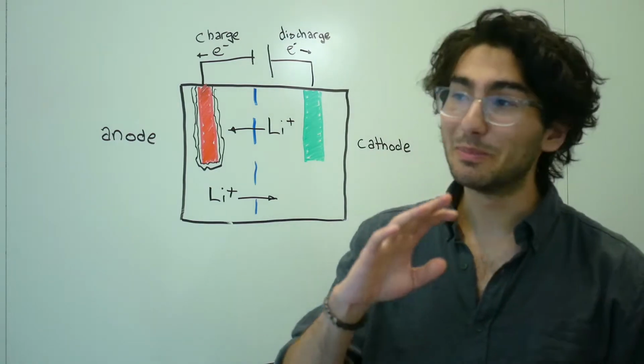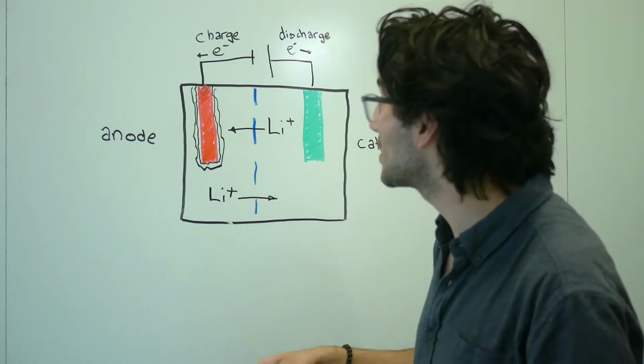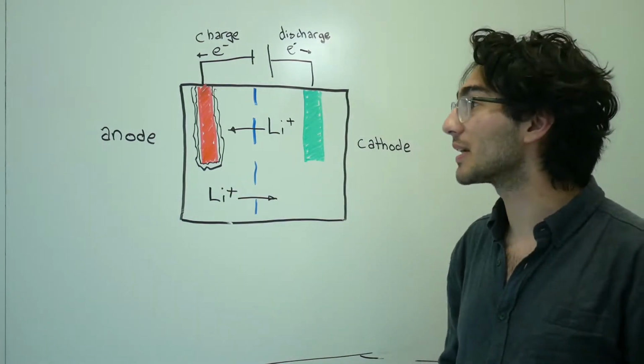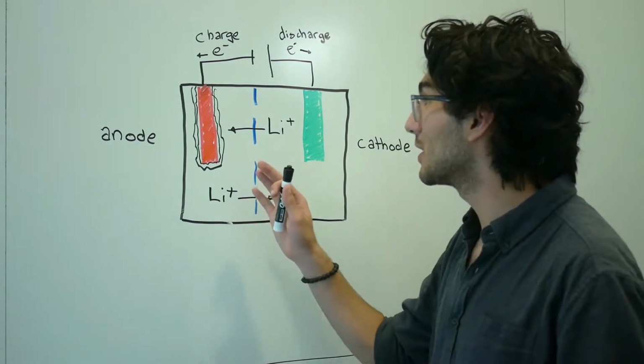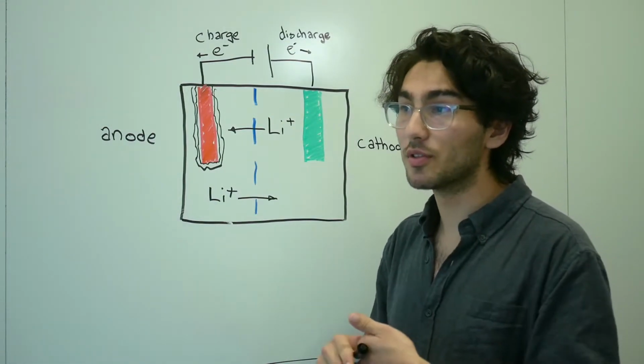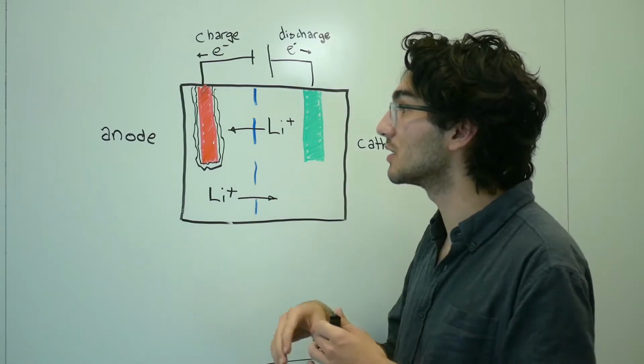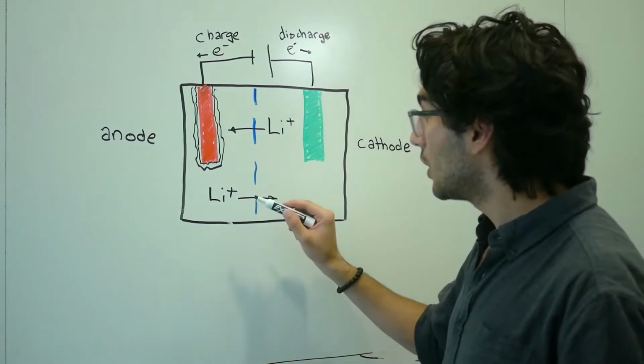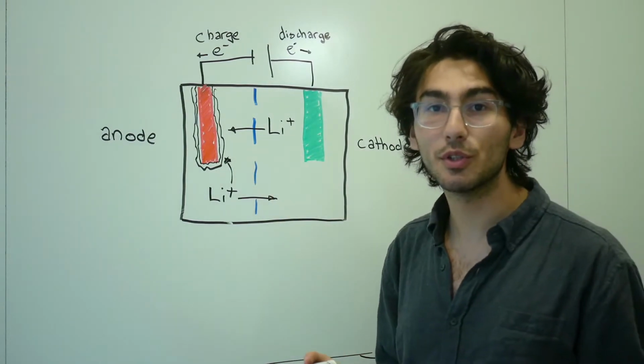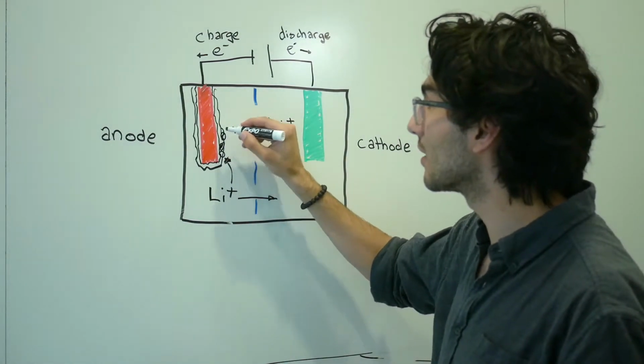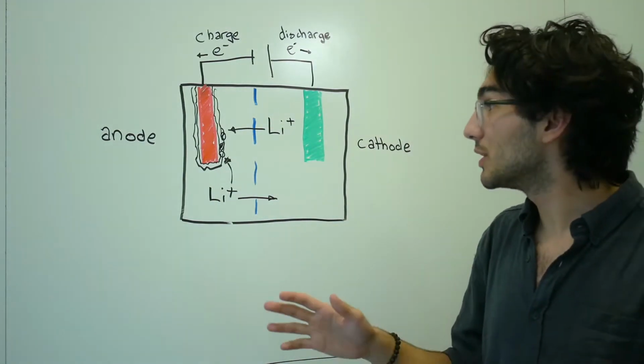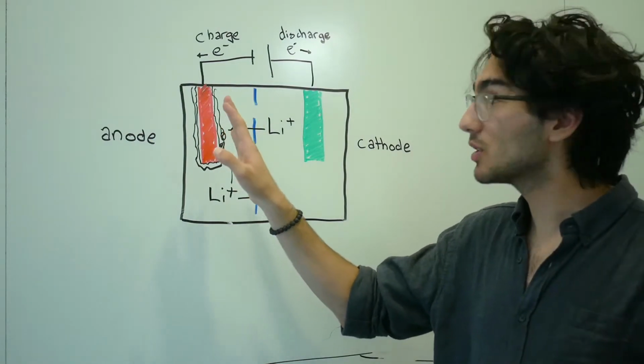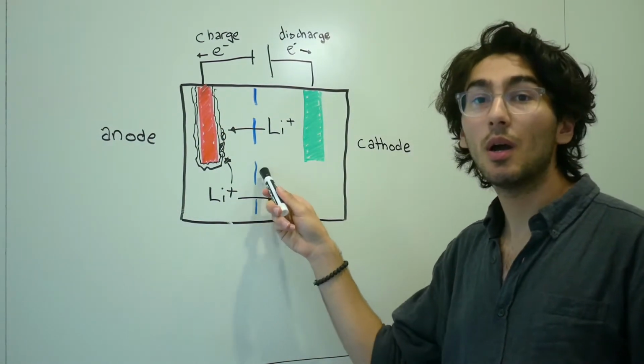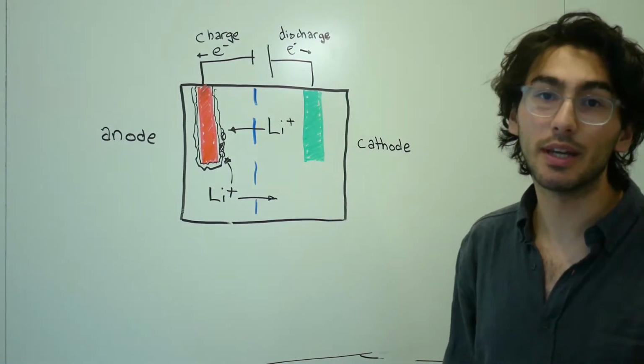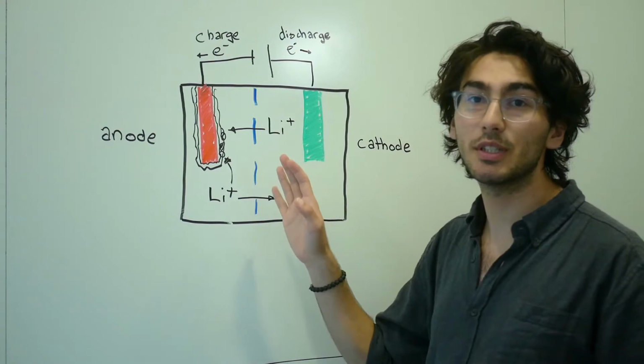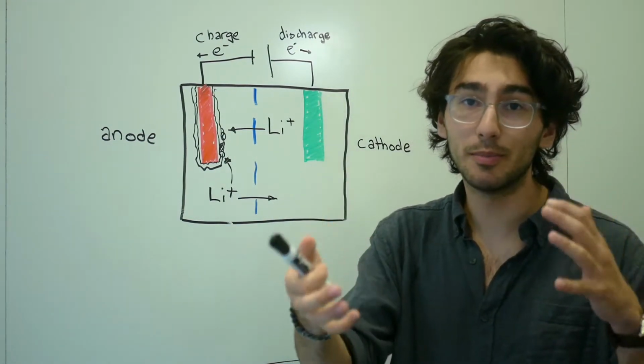Now, the second thing that can diminish your battery health in your cars, phones, and laptops is actually lithium plating. And this is also caused by similar things to SEI layer formation, with over voltage and temperature when you're charging your cells. And basically what happens is you're pulling these lithium ions out of solution and creating a metallic lithium layer on your anode. What that's going to do is cause higher resistance on your anode, and at the same time you're again pulling lithium ions out of your electrolyte, and they can no longer be used for this electricity transfer between anode and cathode, and you're going to diminish battery health.